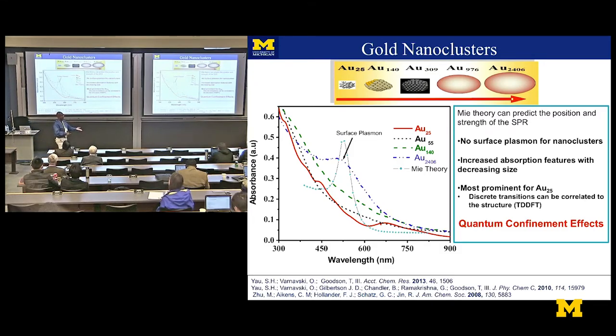What does that mean? It means it's still a drop of metal. It's still conductive. Okay? You can look under the TEM and see a particle there. When you get to 55, there's absolutely no hint of a surface plasmon. And look what happened at 25. Once you get to gold 25, peaks started to happen. It's still a particle. Okay? You know, there's no surface plasmon.